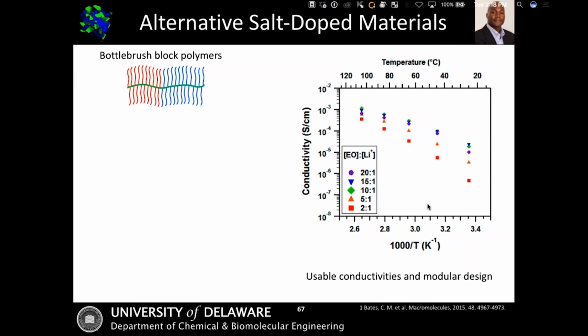So as a couple quick examples, there are things like bottle brush polymers, where in this particular case, I've essentially got a backbone, and basically what I've done is I've essentially polymerized my 2 blocks as brushes as side chains. Now, one of the nice things about these materials is that they retain some of the behavior in terms of the performance or conductivity of higher molecular weight systems, but they're inherently more processable due to their lack of entanglements.